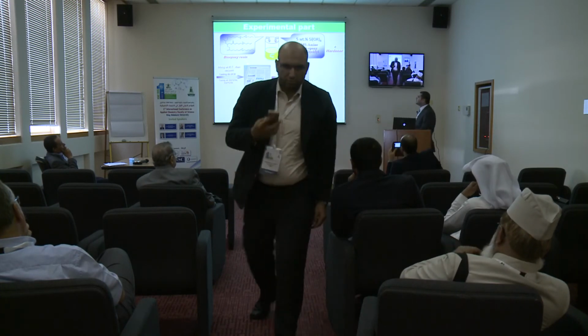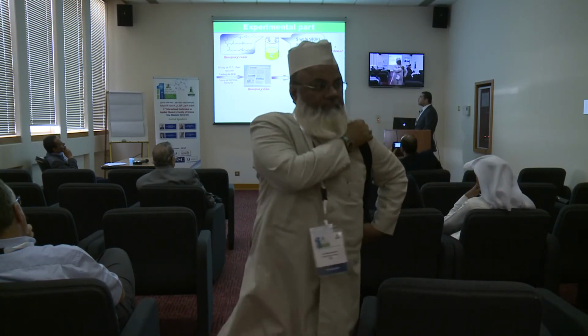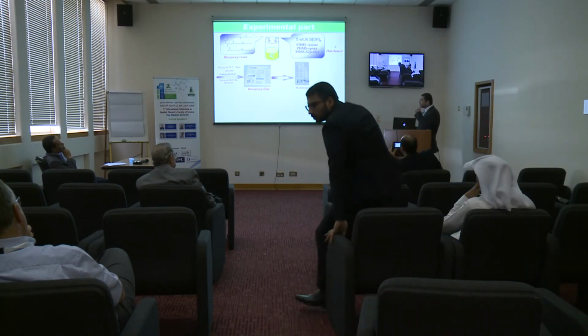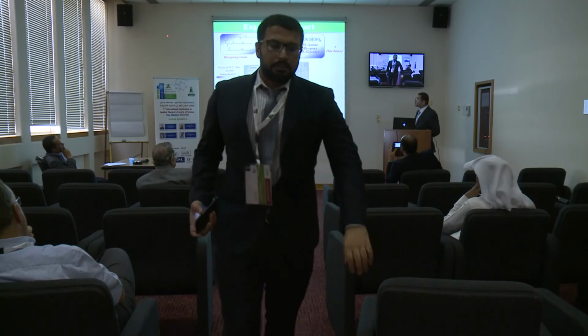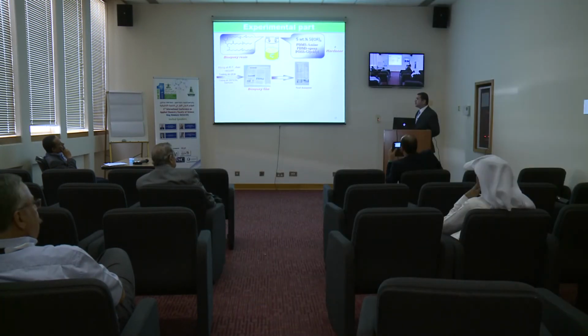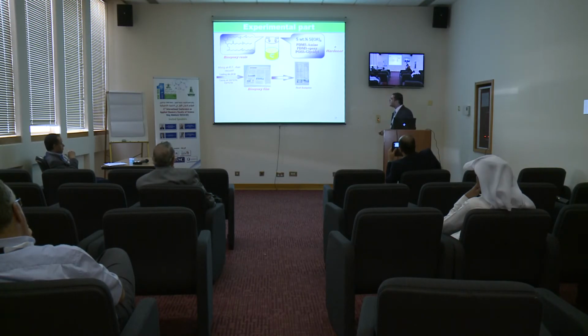We blended bio-epoxy resin with 5% of the amine-terminated or epoxy-terminated polydimethyl siloxane, or POSS-glycidyl, then added the hardener, mixed at room temperature, then vacuum cast at room temperature for 24 hours, then heated at 100 degrees C for 1 hour, then 150 degrees C for another hour to have a film. Then we cut the film to measure the mechanical properties.